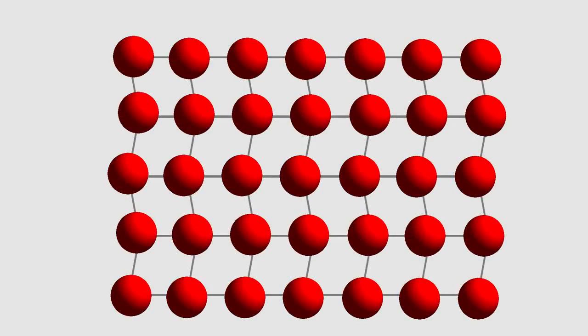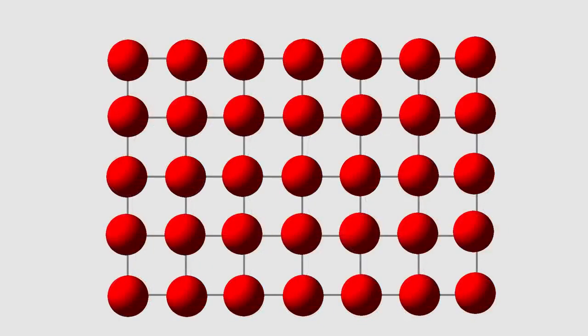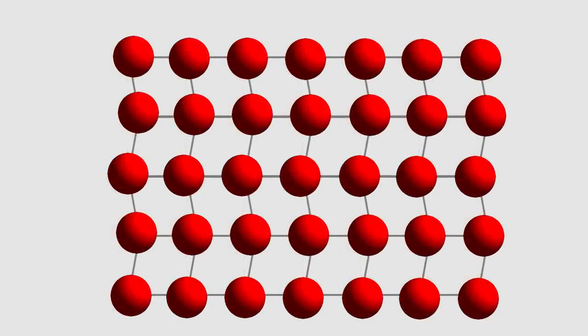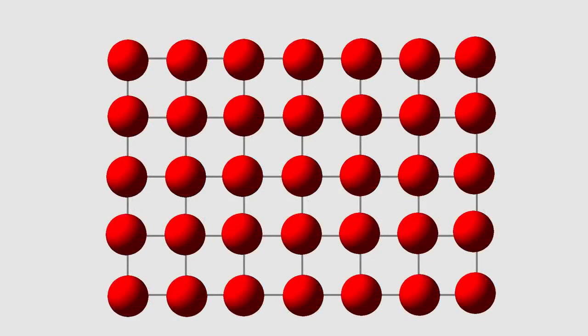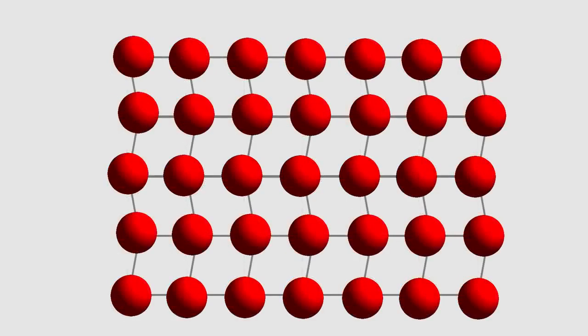When it cools, the crystal structure, the arrangement of the atoms, changes only slightly. Notice that it's very similar. All the atoms are connected in the same way, but the nice, tidy squares are now rhombuses. Notice that even though the atoms move a bit, the overall shape doesn't really change. So, for example, if you fashioned a spring, it still looks like a spring. This doesn't seem very exciting, but this structure has a unique property.